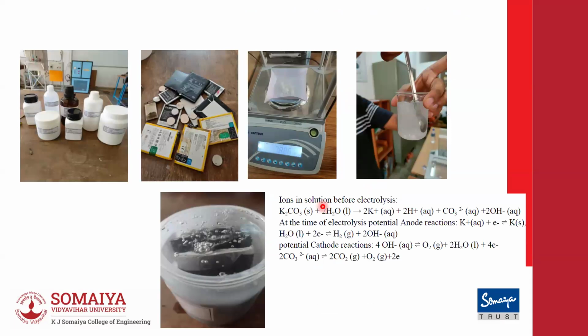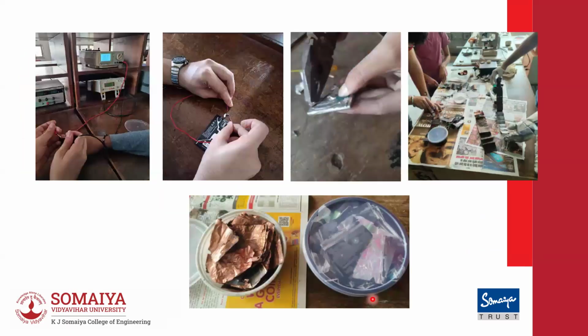We also have looked at some of the battery materials, spent batteries. Now, if you see over here, we have tried out different chemistries. So we basically discharge the batteries, and you can see the discharging process. Slowly, you'll see the bubbles coming up, and the moment the bubbling stops, that's it. After that, we also tried short circuiting it. After opening the batteries, we opened up some of these prismatic ones, as you can see over here, and we separated the copper foils and the aluminum foils.